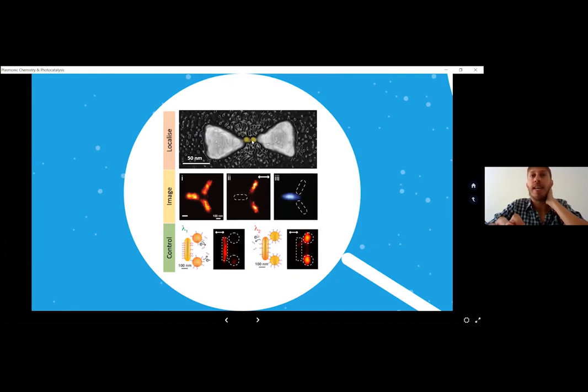We used a trick here: we chemically functionalized these gold nanoparticles with something that reacts with the molecules that have been converted on the surface of these nanoantennas after we illuminated with the plasmon resonance wavelength. Here we can see that these two particles bound mostly in the hotspot, meaning that the reactions in this kind of plasmonic structure started at the hotspot indeed.